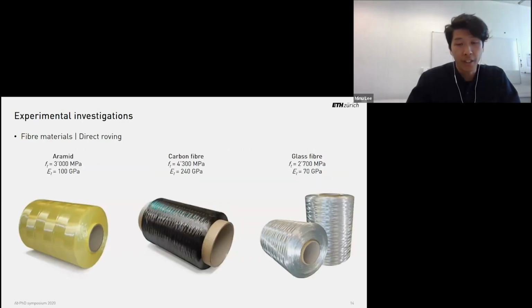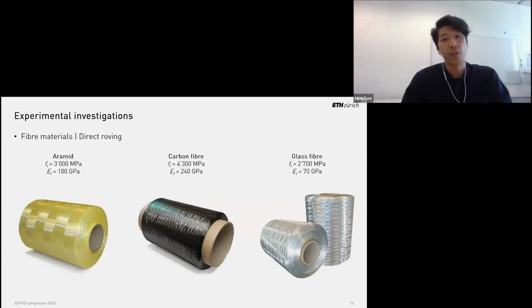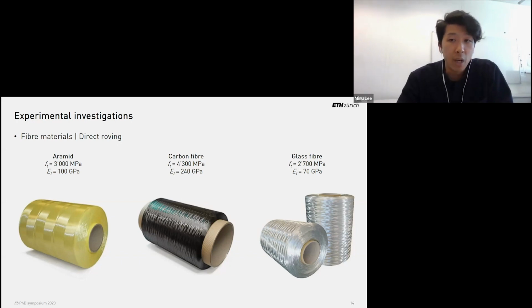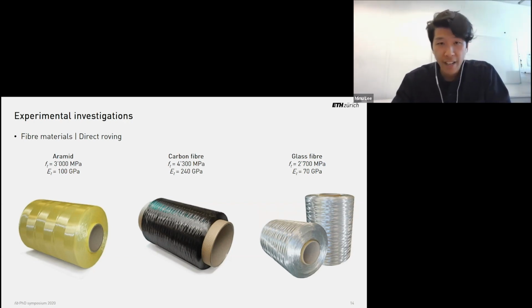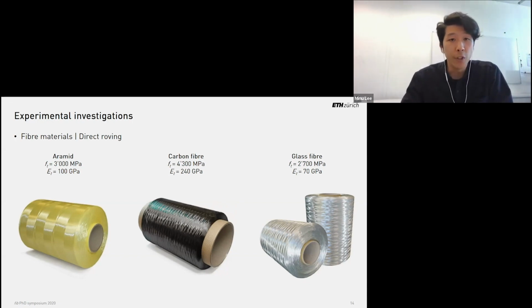So after looking at different knitting patterns, there were also 3 different fiber materials that we tested: aramid, carbon, and glass fibers. They all have a high strength between 2,700 megapascal and 4,300 megapascal. This is in respect to the filament strength, not the roving strength, and moderate to high elasticity modulus. For the directly knitted reinforcement, only aramid fibers were used, since these were the only ones that could be knitted.